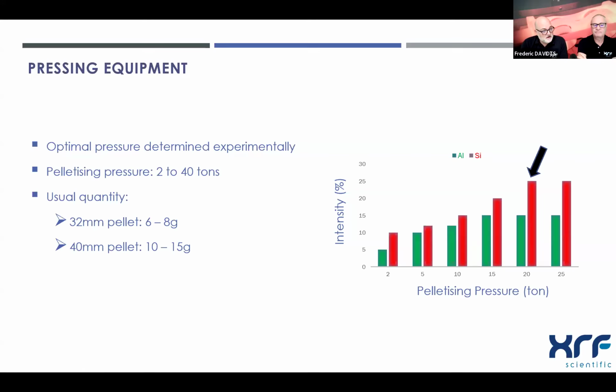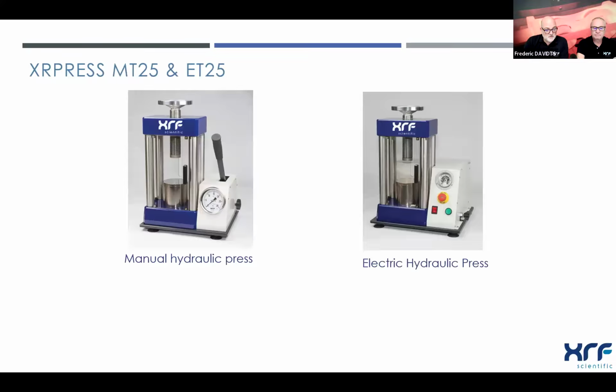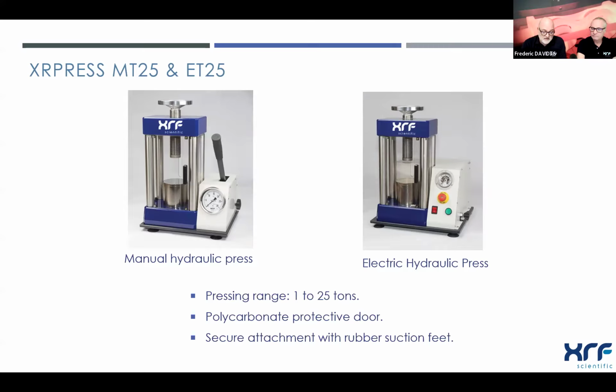So the usual quantity of powder, I would say the mix of binder and sample, is between 6 and 8 grams for the 32 millimeter pellets, and between 10 and 15 grams for the 40 millimeter pellets. And the pelletizing time is not so important, to be honest, but nevertheless it's better to keep it about the same time for each pellet. But if you put 10 or 20 seconds, it doesn't matter so much for the pressed powder tablet. So the equipment we have available, we have the classical manual hydraulic press and also the electric hydraulic press. Both presses, the XR press, are able to reach 25 tons. And so, to be honest, they cover nearly all the applications you can find for all the materials.